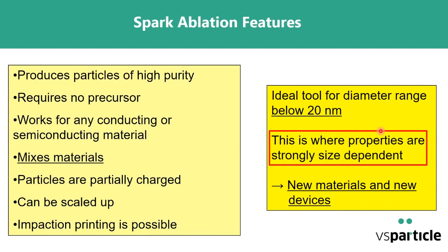Let me mention some features that actually make this method interesting. And of course, all of that I didn't know when accidentally I had sparks in my setup and found that it was a useful method. Back then, of course, I had no idea of how useful it would turn out to be. It can produce particles of high purity. It requires no precursor, as most other methods do, because it converts the material of the electrodes directly to nanoparticles. It works for any conducting or semiconducting material. And this is the most important point. It mixes materials. We can use this technology to mix materials in a very versatile manner, and I will come back to that. The particles are partially charged.